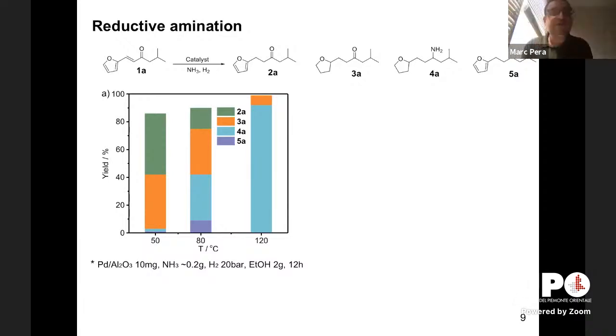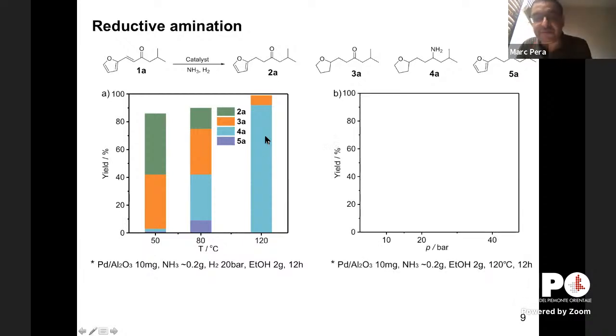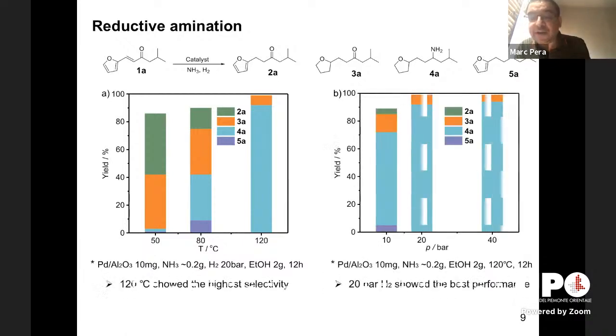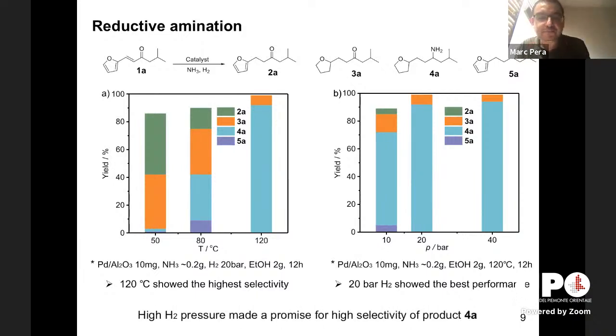Okay, I continue. So the temperature will influence a lot the catalytic behavior. This is for palladium alumina. We'll see that 120 degrees is a good temperature. And also the hydrogen pressure will contribute to these results. So we optimize the conditions. We can have product 4A, the most stable one thermodynamically, with high yields.